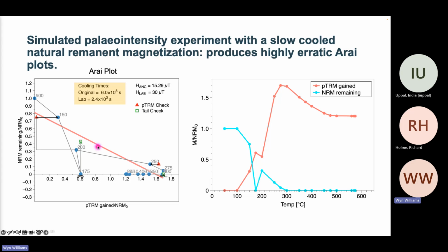Then we've got a PTRM tail check, which is basically demagnetizing things twice to see if we can get rid of any magnetization we've put in there. So this is really a test of reciprocity. We put in the magnetization in the laboratory and we're trying to take it out. We should be able to take it all out. If we took it all out, the PTRM tail test would be 0, but clearly it's not. It's massive.